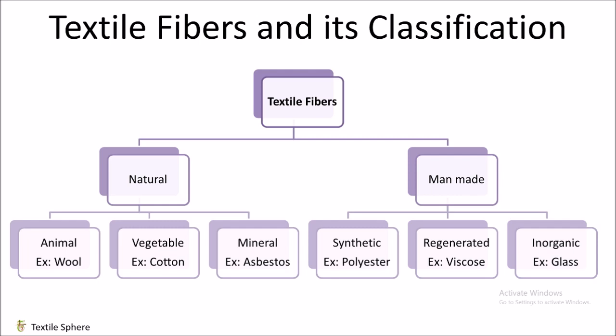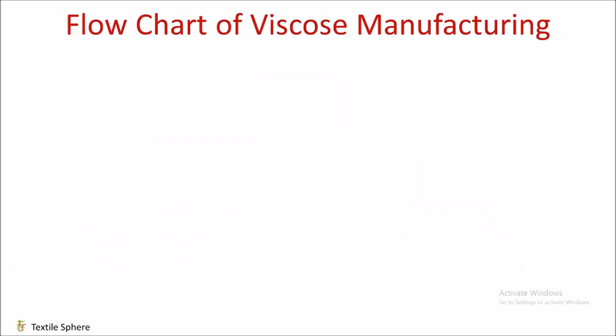This was all about the classification of fibers. Now let's discuss about the process flow of manufacturing viscose fiber. The manufacturing of viscose rayon involves various steps, right from steeping to wet spinning. Steeping is the very first process in the manufacturing of viscose. In this process, the pulp is treated for mercerization in the presence of NaOH at mercerizing strength. The pulp sheets are then steeped in 18% NaOH, and alkali cellulose is generated as the product during the reaction.